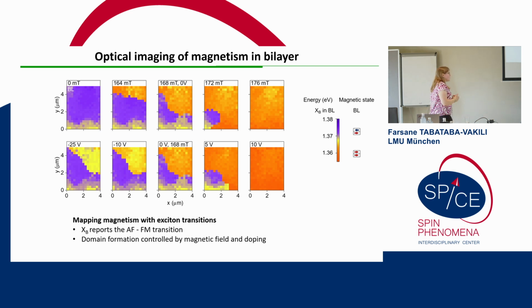And then, since the exciton energy is correlated with the magnetic order, we can use this to optically image the magnetism in this material. Very indirectly, of course. What I'm showing here are raster scan differential reflectance measurements of a small area of the bilayer of around 5 by 4 microns, where color-coded in purple is the exciton energy in its antiferromagnetic state and in orange in its ferromagnetic state.